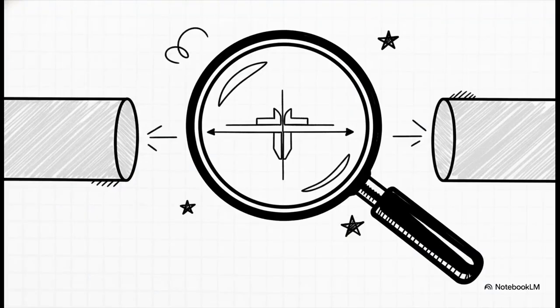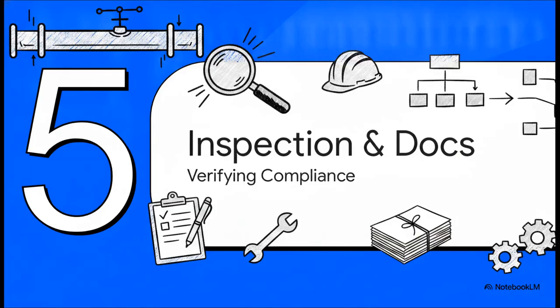The stakes here are just incredibly high, so as you'd guess, the tolerances are incredibly tight. Standard wall pipes up to 20 millimeters thick literally cannot exceed a 3 millimeter misalignment limit. Now, if the pipe wall is thicker than 20 millimeters, they do give you a slight allowance up to 4.0 millimeters. But adhering to these tiny numbers is really the only way to guarantee complete penetration and fusion of that weld.